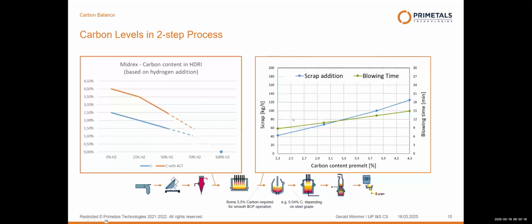What is the consequence? Just having a look on the right picture here, we have done calculations for a typical BOF converter, 0.04% carbon at tapping. Of course, the lower the carbon content in the pre-melt, the shorter is the blowing time. So while today, from this example, we had some 15 minutes pure blowing time, we would go down to 9 minutes if we just have a carbon content of 2.3%. Might sound good for the steel plant operation because the converter is getting faster and you are more relaxed and less a bottleneck in the production.